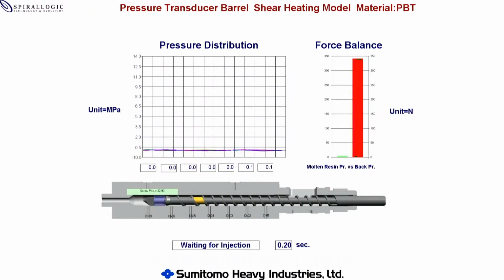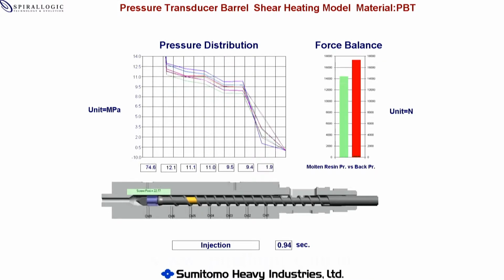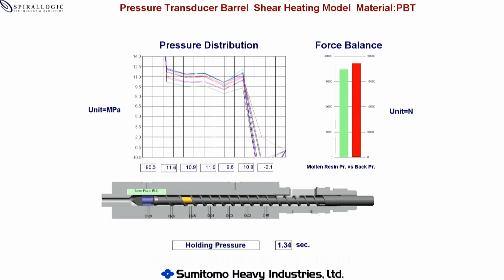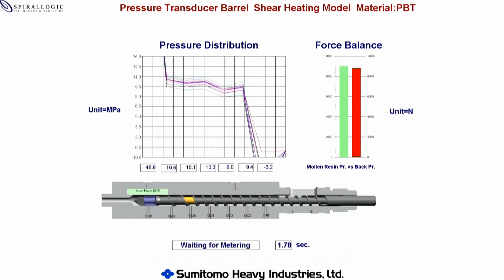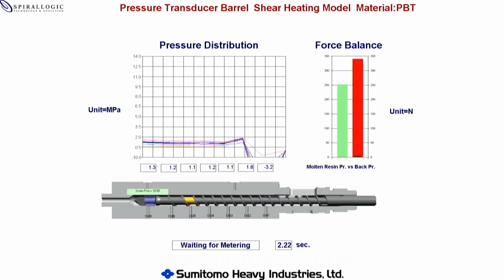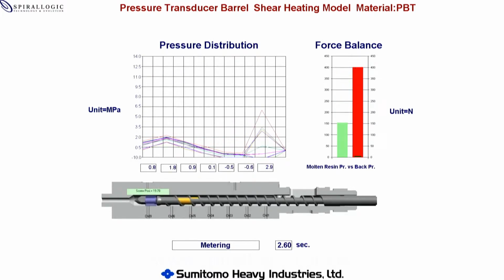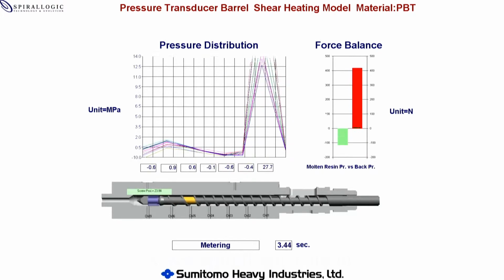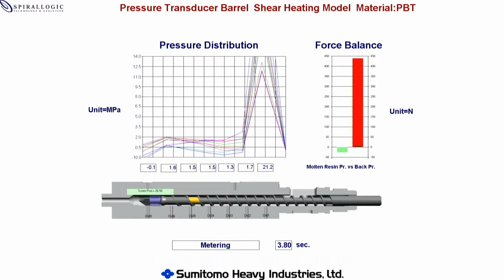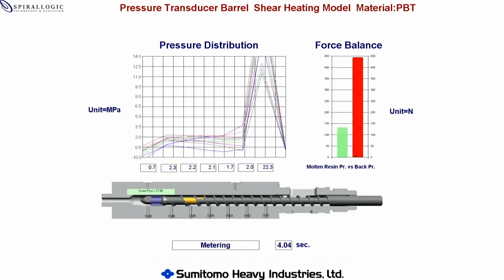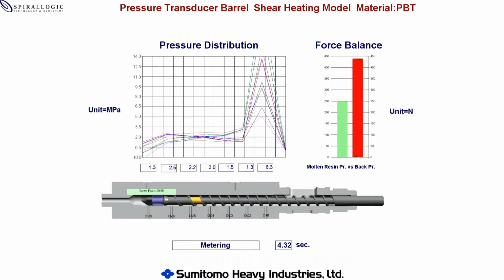The machine was equipped with 7 pressure transducers along the barrel axis to confirm how friction energy in the barrel is generated. This graph shows 10 cycles of the pressure inside the barrel. Now, metering is started. You can see a very high pressure rise in the feed zone. This is showing where high friction is generated. And at the end of the screw, the molten resin has extreme pressure variations.